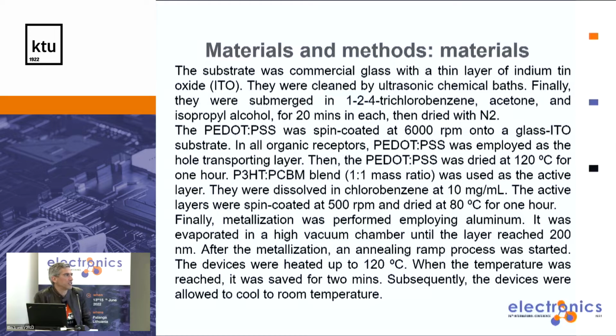Well, here we have a video that, if we have time, maybe we can show at the end of the presentation. It's about 4 minutes, and it's the explanation of the fabrication of our OPD. But more or less, this is the explanation of the video, if it's not possible to see. So first of all, the substrate was commercial glass with a thin layer of indium tin oxide. They were cleaned by ultrasonic chemical bath. Finally, they were submerged into 1,2,4-trichlorobenzene, acetone, and isopropyl alcohol for 20 minutes, and then dried with nitrogen.